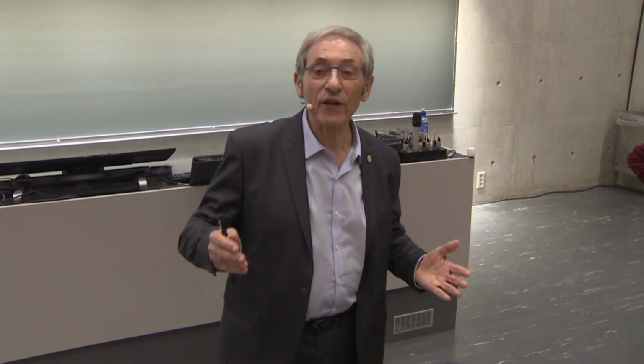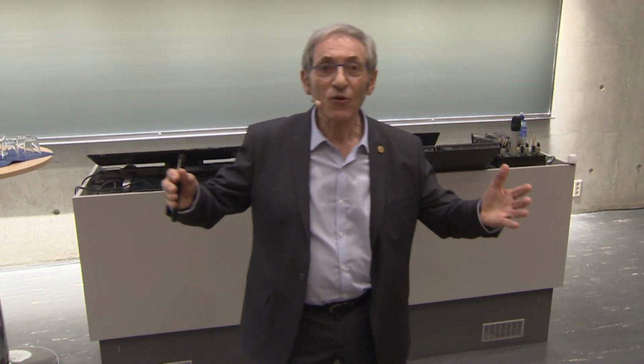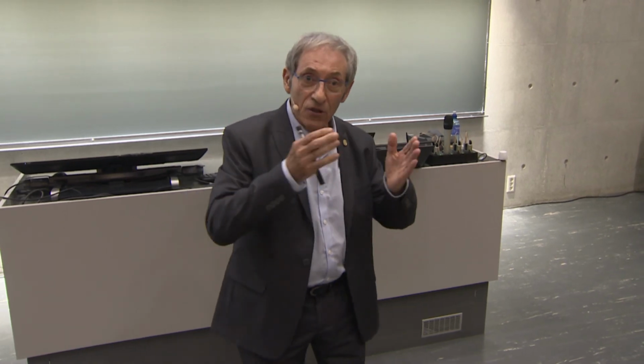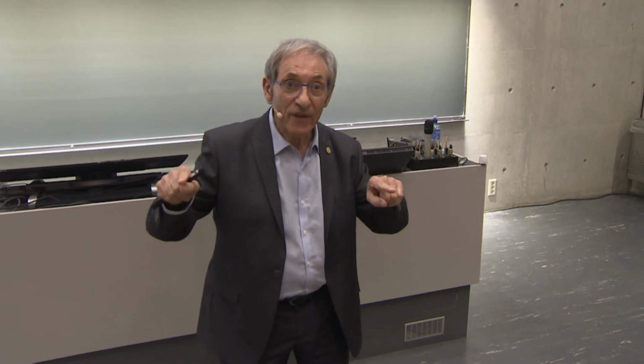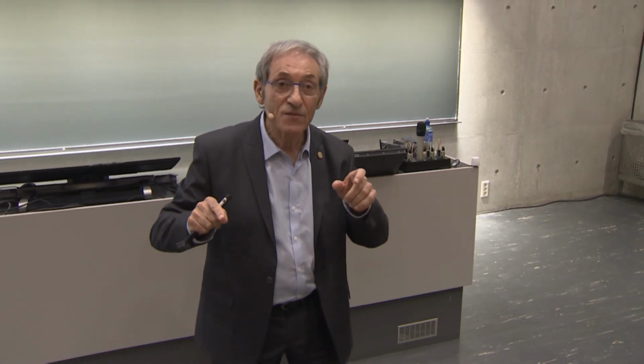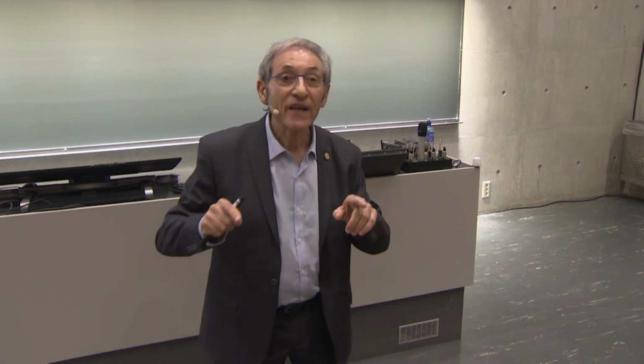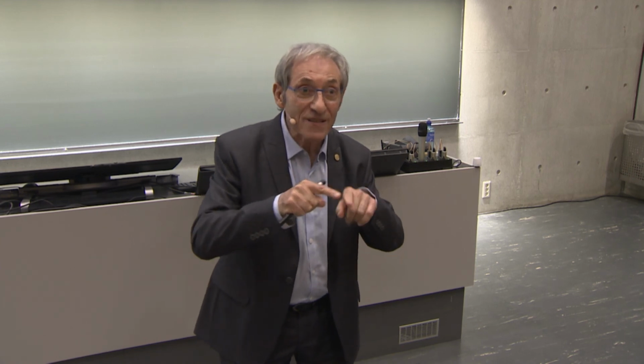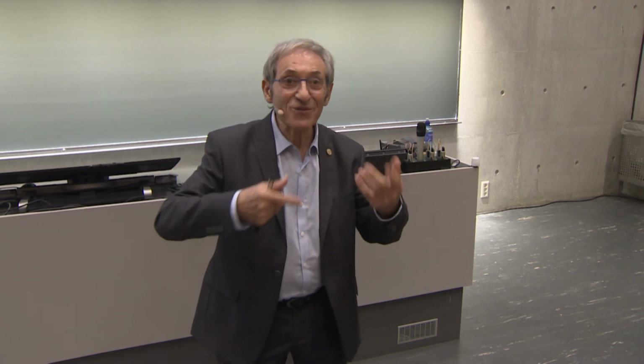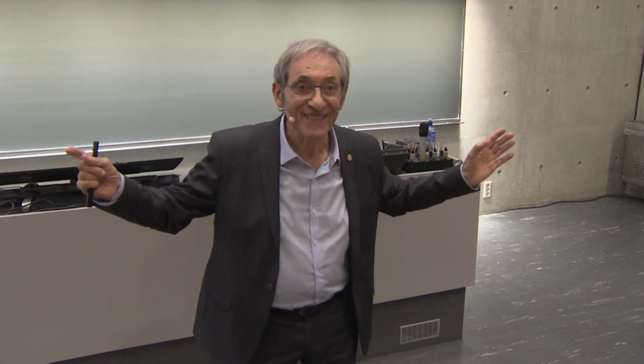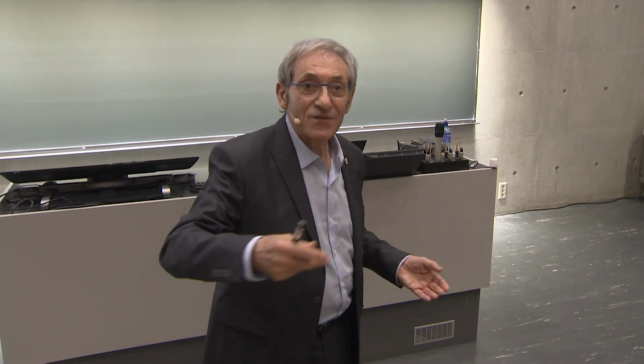But it must be continuous. We have a lot of control experiments here, of course. One thing is to make not a continuous line, but a broken line with gaps between segments. If the gap between segments is more than 30 nanometers, it is insulating. If we start closing the gap below 30 nanometers, it starts conducting. This is probably the resolution of our lithography. So this is a way to check what is going on. A nominal 25 nanometer gap is a perfect conductor. But of course, if it is not continuous, it doesn't conduct. Of course, we have to check for leakages and all this, as I told you. So one way to check is to make the same line, but not a continuous one, insulating.